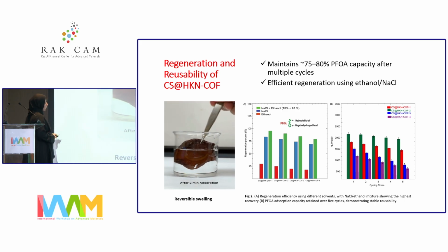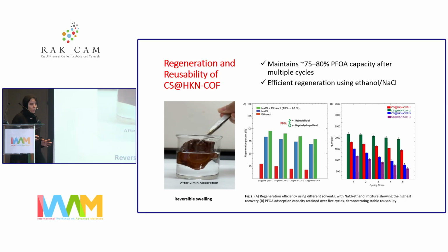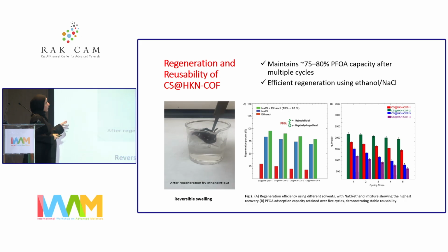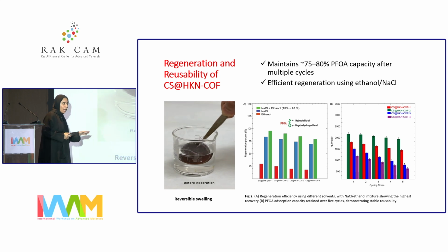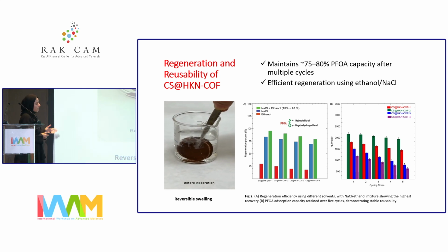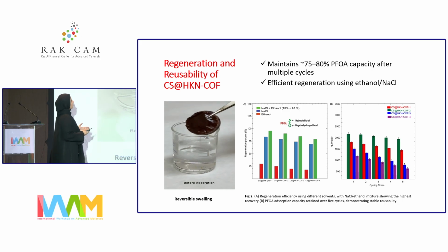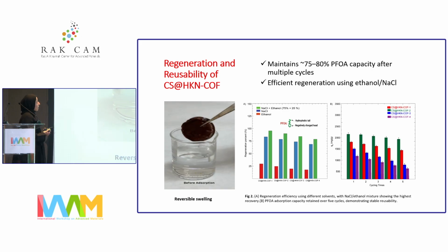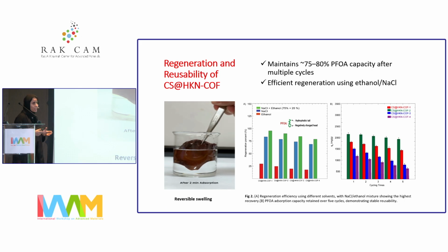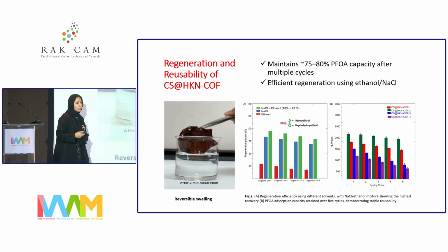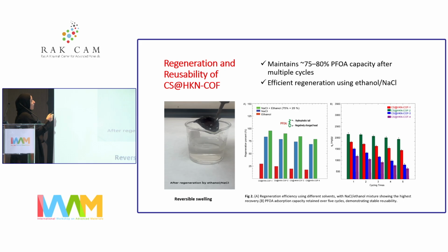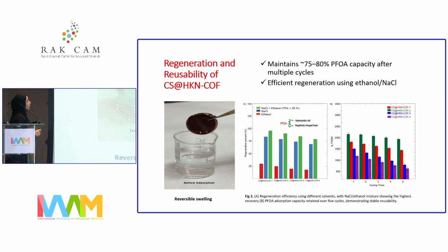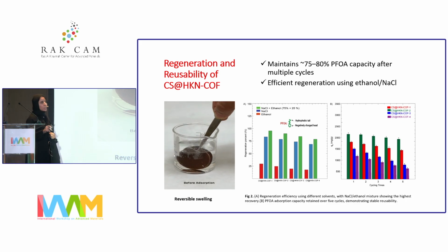And if you look at this video that shows reversible swelling, actually we did this experiment. The membrane of hybrid material, we immersed it in perfluorooctanoic acid, and after 2 minutes of adsorption, the membrane expanded to double its size. Okay, maybe you'll see now, it expands to double its size in order to allow more adsorption of the perfluorooctanoic acid molecules. Then it goes back to its original size when we immerse it in the regeneration solvent, which is sodium chloride with ethanol. And this behavior, this response, is reversible.